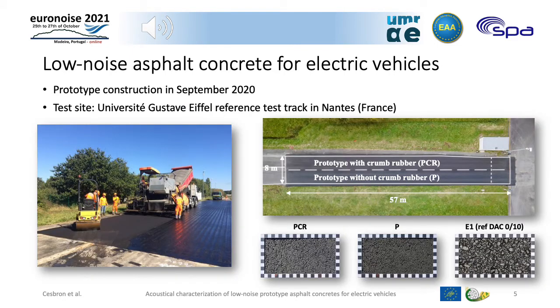The prototype construction was performed in September 2020. It was built on the Université Gustave Eiffel reference test track in Nantes in France. As you can see on the picture, the prototype was 57 meters long and 8 meters wide. It was divided in 2 test sections, PCR with crumb rubber and P without crumb rubber. At the bottom of the slide you can compare the final state of the road surface for test sections PCR and P in a frame of 20 cm by 10 cm. You can compare to test section E1, which is the reference within this study and is a dense asphalt concrete 0/10.